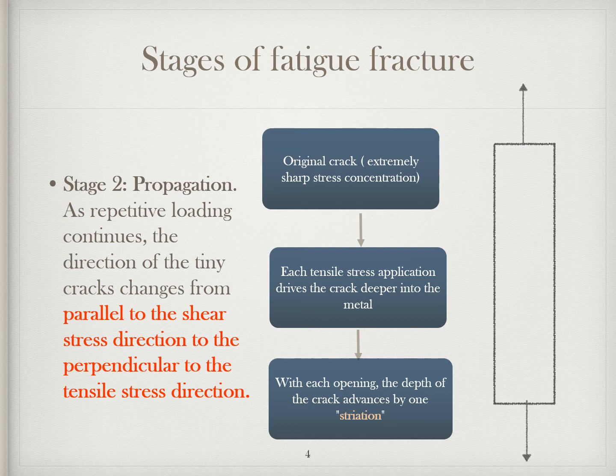Because the second or the propagation stage of fatigue is usually the most readily identifiable area of fatigue fracture, it is necessary to briefly mention how the fracture progresses across the section. After the original crack is formed, it becomes an extremely sharp stress concentration that tends to drive the crack ever deeper into the metal with each tensile stress application.